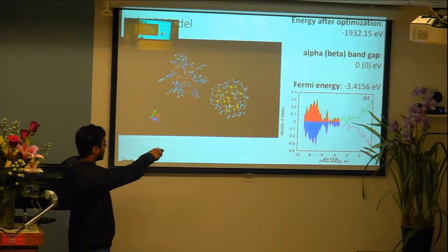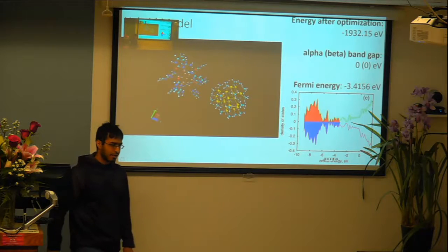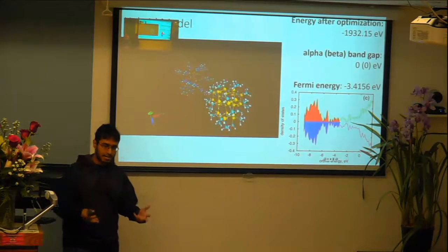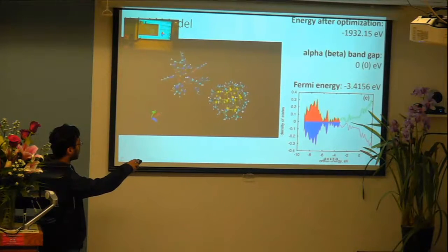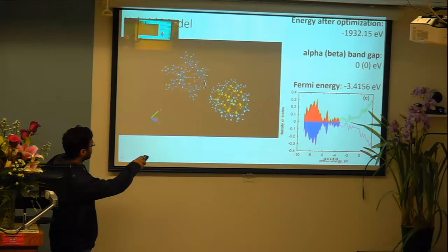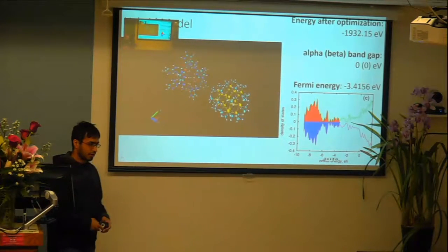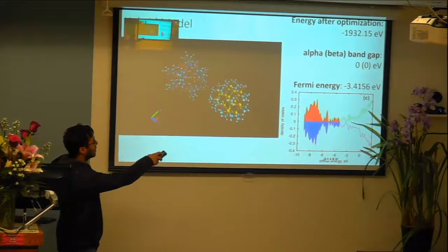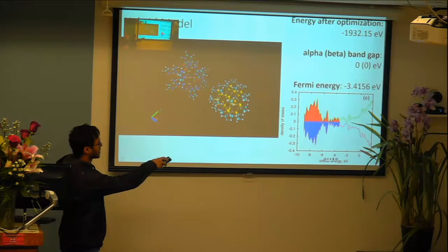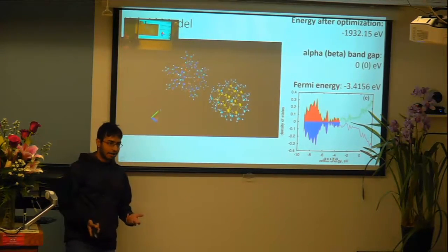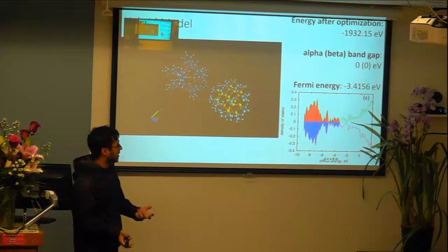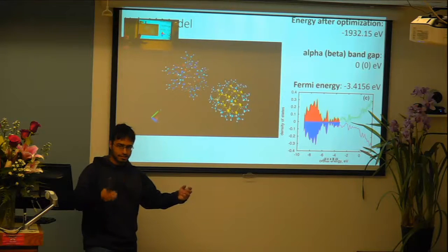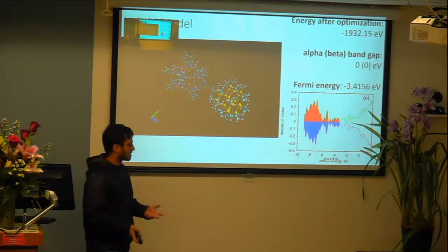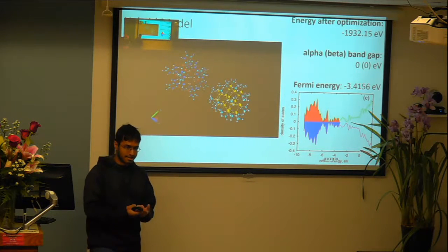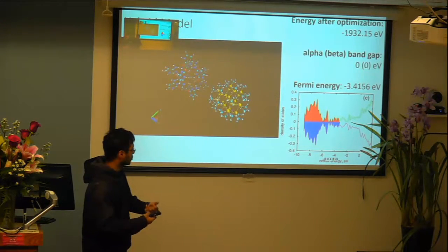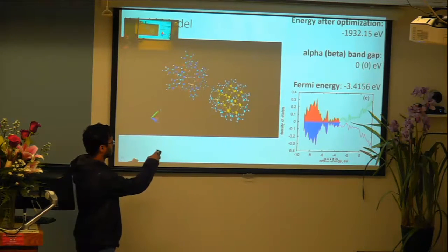And on this slide, here's a model where we took both nanoparticles and put them in the same simulation and optimized the entire model at once. So we have both of the nanoparticles being optimized at the same time, and the total energy after optimization is actually a little bit higher than the separate energies after optimization for the silicon nanoparticle and the silver nanoparticle, which signifies that the binding energy is actually positive, and therefore the two nanoparticles would want to actually repel each other when brought close together.